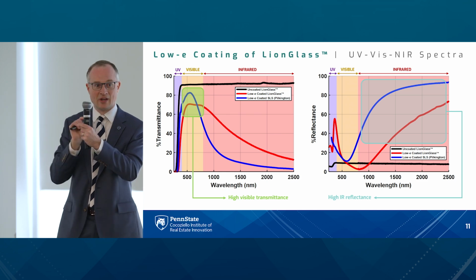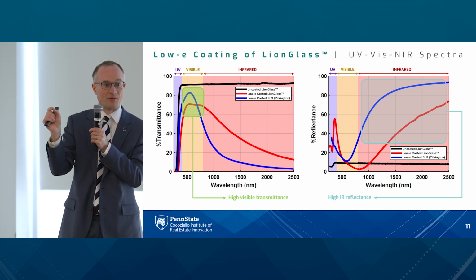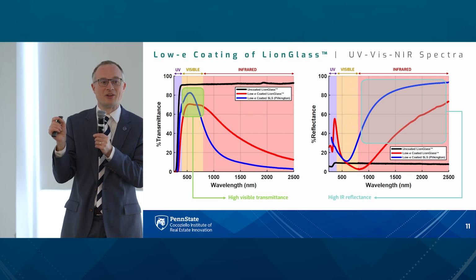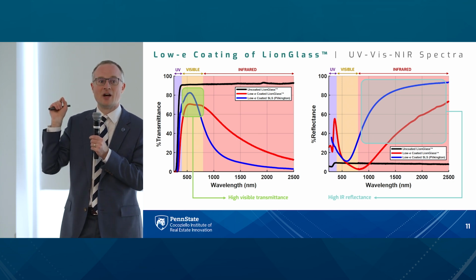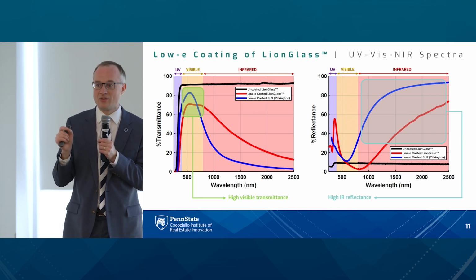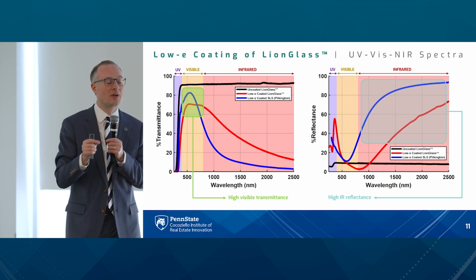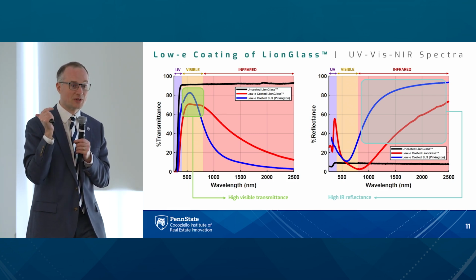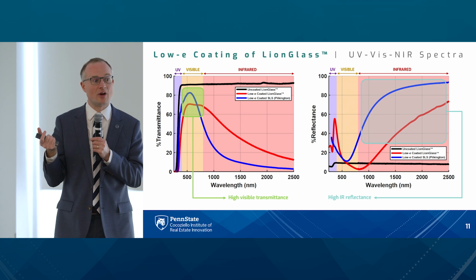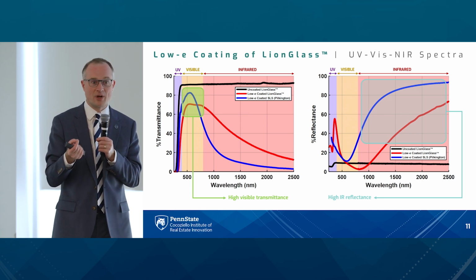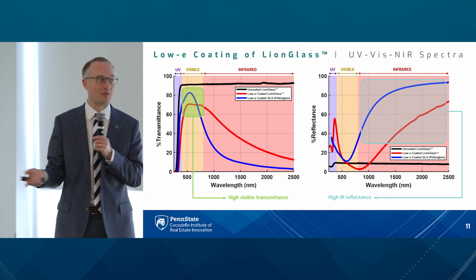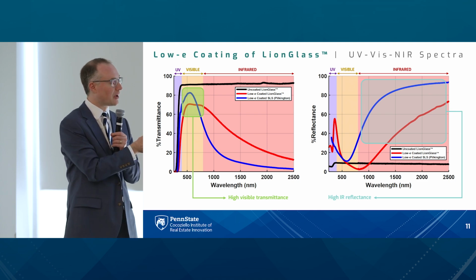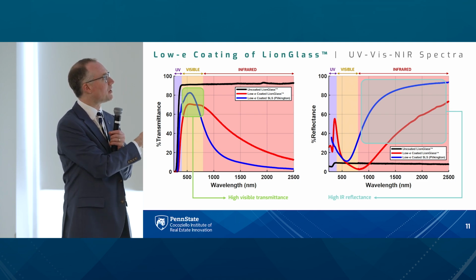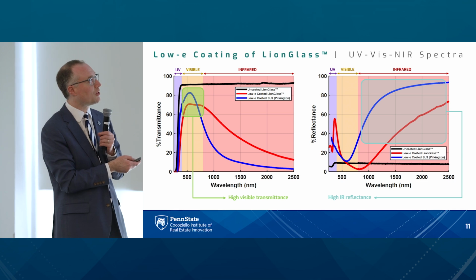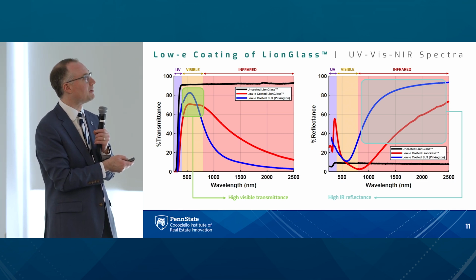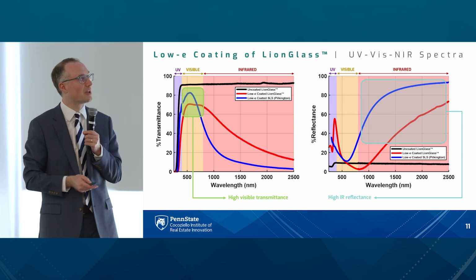Like if you take a window and you look at it through the width rather than through the thickness, you'll notice it's not actually clear. It's green, and it's green because of iron contamination in the soda ash and in the limestone. First of all, we're getting away from those batch materials, but also Lion Glass can tolerate a greater amount of contamination from iron before it actually shows any visible coloration. So it's actually clearer compared to soda lime, and you can compare then the transmission spectrum of the coated Lion Glass sample in red versus the coated soda lime sample in blue.